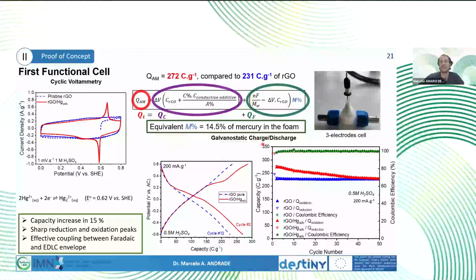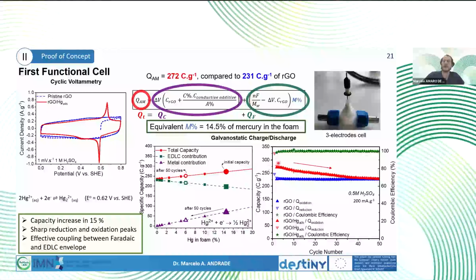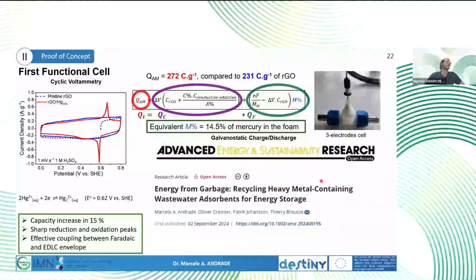Right, these are galvanostatic charge curves. We see the mercury oxidation peak here. We see the mercury reduction peak here. So that was really clear that that was an electroactive cation adsorbed on the surface. But we see a decrease in capacity with time, and we needed to understand this decrease. So that was also another scientific question. All this work and this proof of concept was published in Advanced Energy and Sustainability Research. That was the first article of this thesis, and that's where the motto energy from garbage comes from.